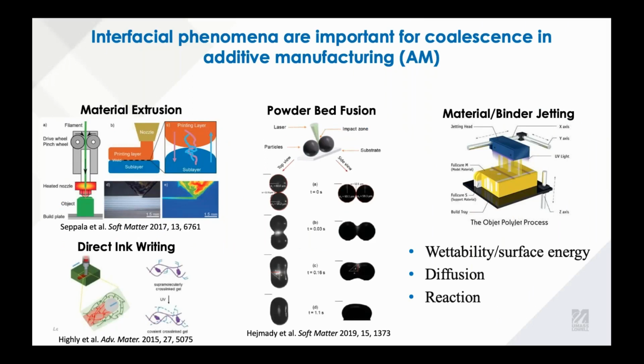Because additive manufacturing is additive by nature, we're trying to coalesce components, and whether the smallest component is a bead of material in material extrusion or direct ink writing, or if we have a powder bed where we're trying to have fusion, we have these coalescence events, and in all of these cases, they're interfacial phenomena that are dictating the time scales and the success of this coalescence. Examples of this include wettability, which is dictated by surface energy, and then also things like diffusion or a reaction, depending on the additive manufacturing technology. So next slide.